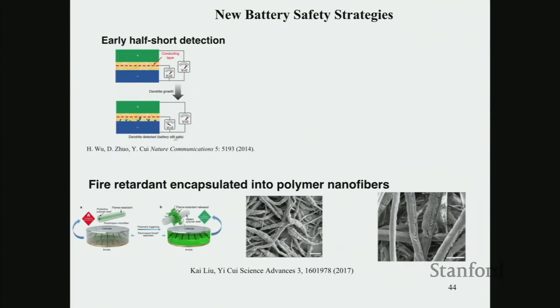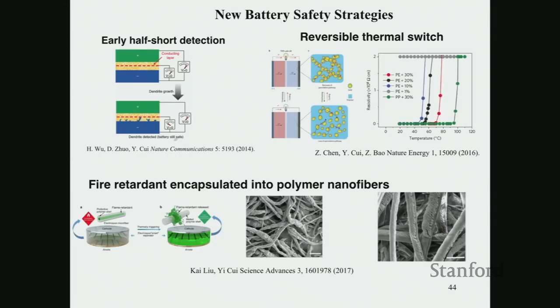We can put fire retardant encapsulated into a polymer, for example. You can put in this green color, fire retardant encapsulated into the polymer. The polymer's melting point can be engineered to the temperature you want, for example 100 degrees Celsius, around that. If you get to that temperature, the polymer melts and then releases this fire retardant. So you can prevent a battery from catching fire. We have also worked with Professor Zhenan Bao in chemical engineering to say, well, let's find a switching mechanism to make the battery safer.